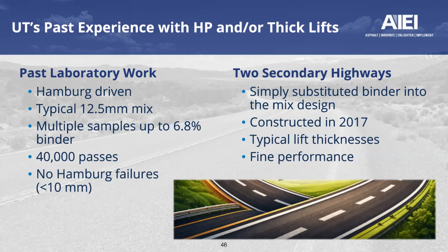But the initial projects that they went to the field with were typical Superpave projects where they did a substitution of a 64-34 binder at design and substituted in the highly modified 76-34 binder. Both of those were constructed on secondary highways in 2017, done to typical lift thicknesses, and the performance has been no reported distresses of any significance thus far at almost 9 years of service.